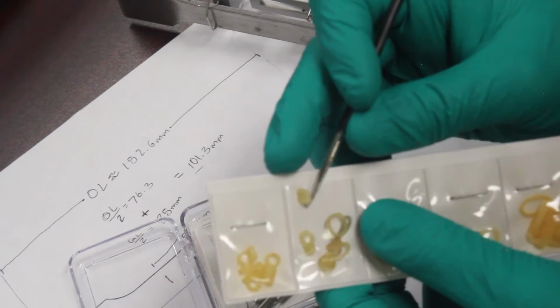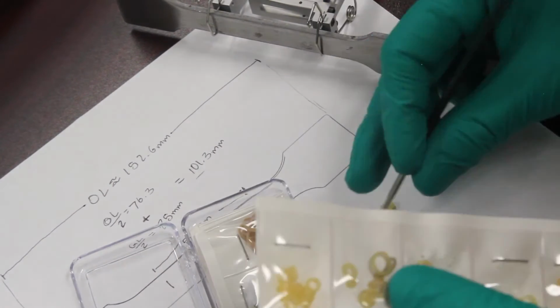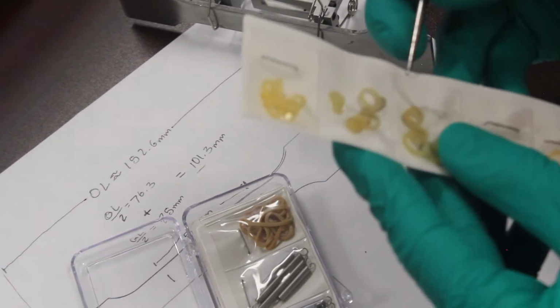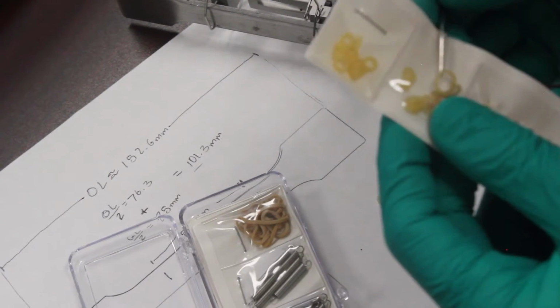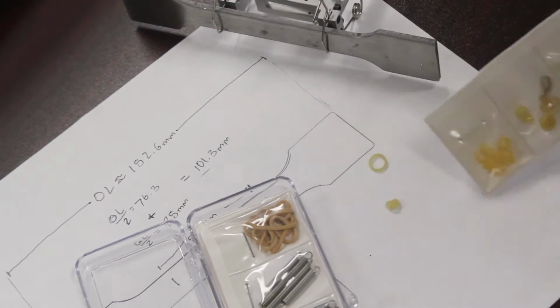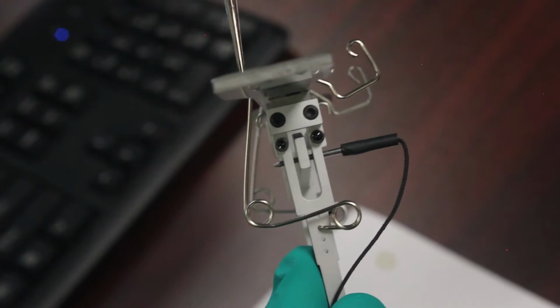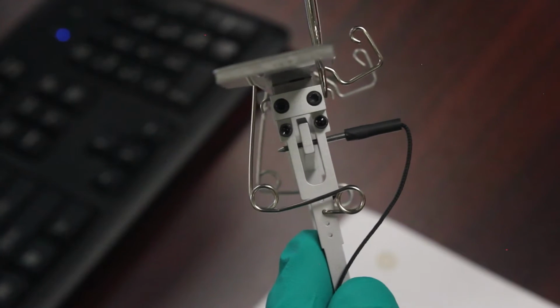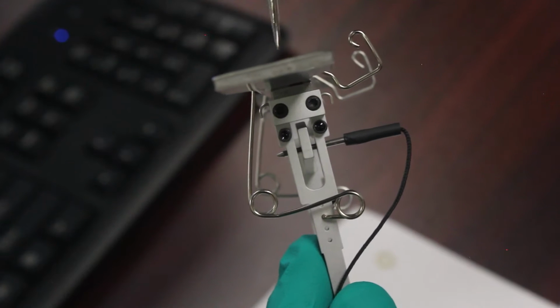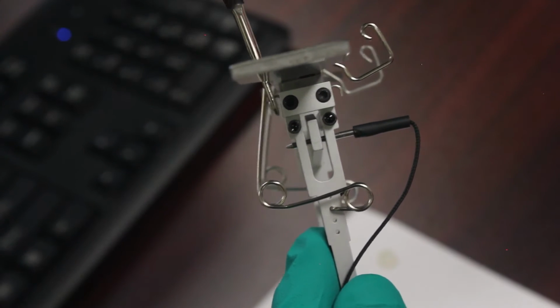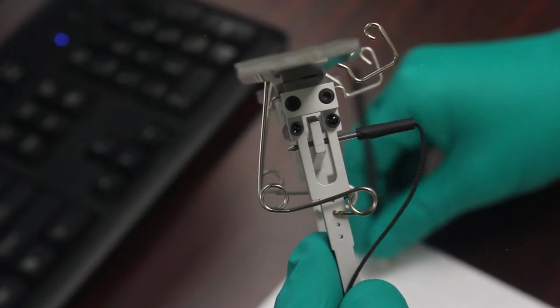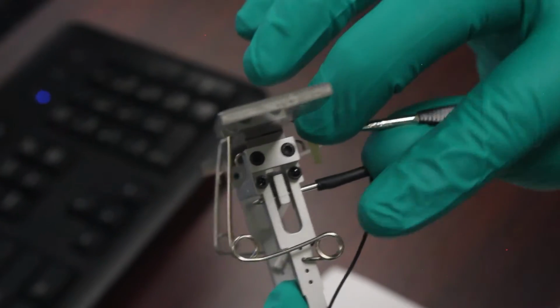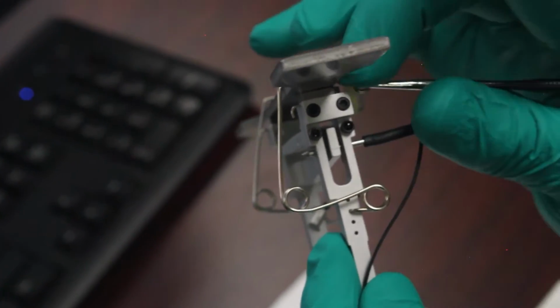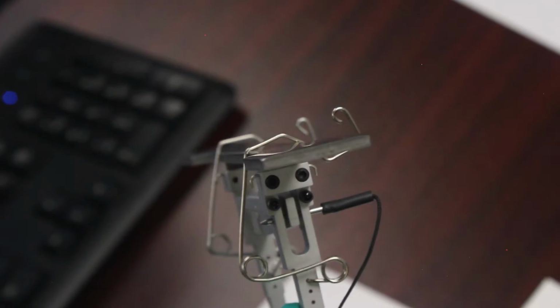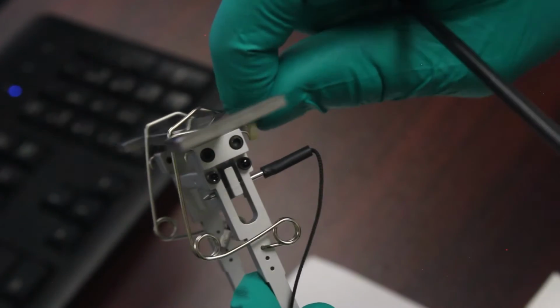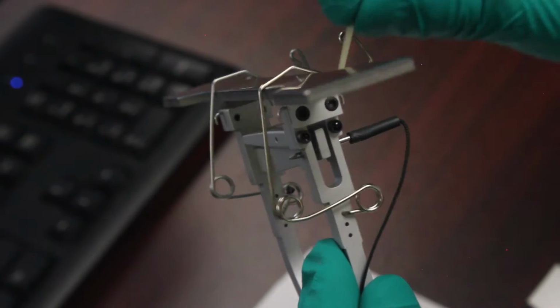Get 2 small rubber bands from the little bag of rubber band pouches located near the tensile tester. We're going to stretch these small rubber bands across the 2 hooks located here on around each knife edge of the extensometer. Using the pick tool or your fingers, stretch a rubber band from one hook over the tensile sample to the other hook in order to keep your tensile sample planted firmly against the extensometer.